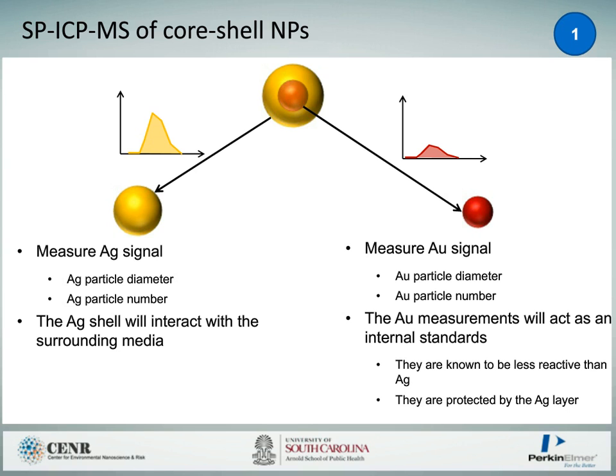The gold will act as the internal standard. So the gold is less reactive than the silver, but it's also protected by the silver layer. So really this shouldn't change. We should have the same particle number and the same particle size as long as nothing's happened to the whole nanoparticle system, like aggregation. So if the particle number for both gold and silver decreases, when the particle diameters for both gold and silver increase, then we're likely to be getting something like aggregation occurring.